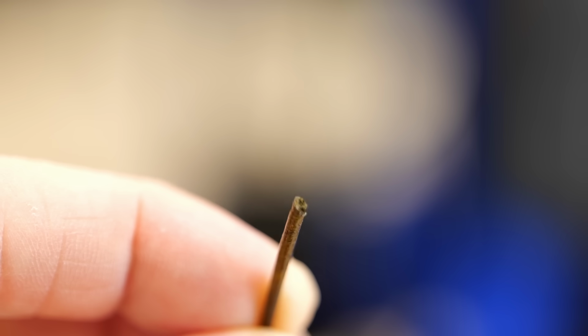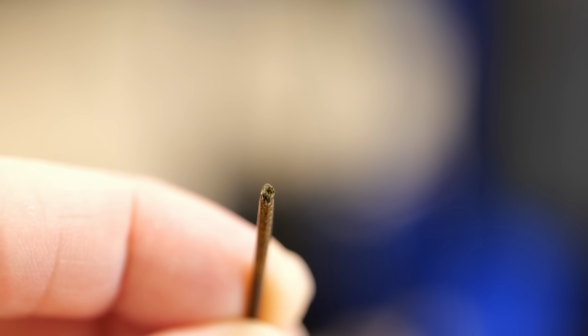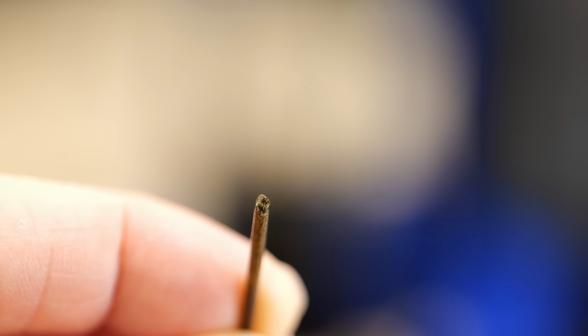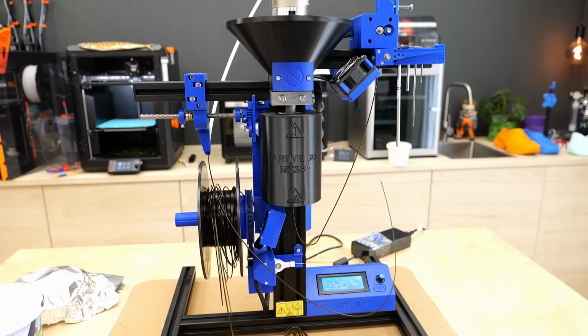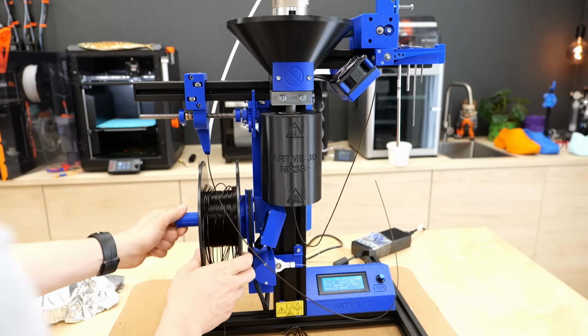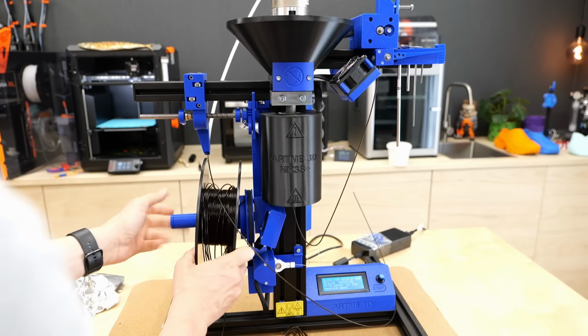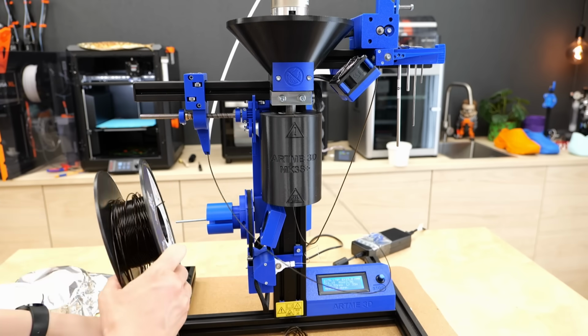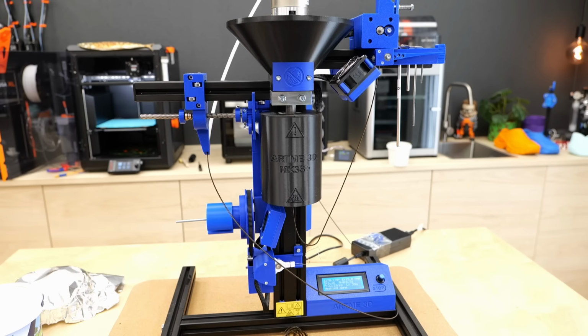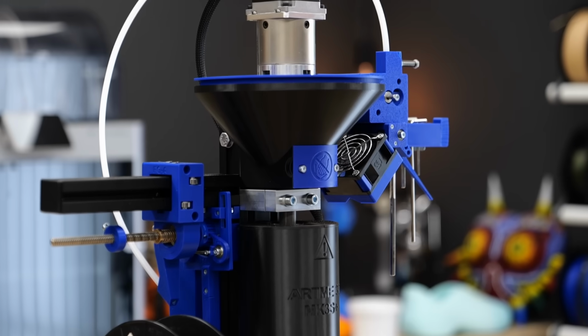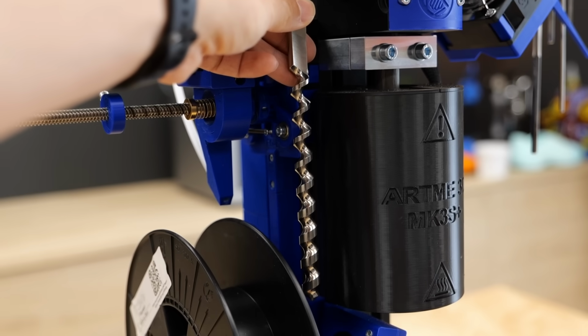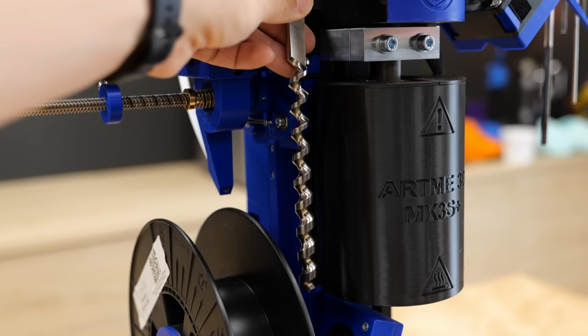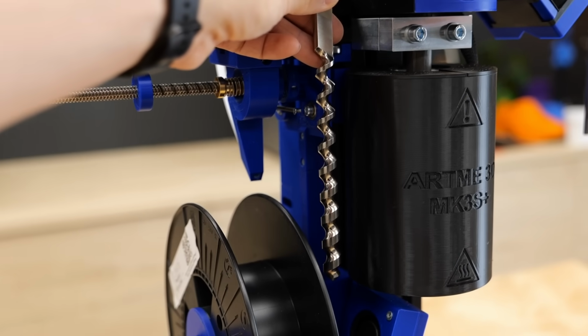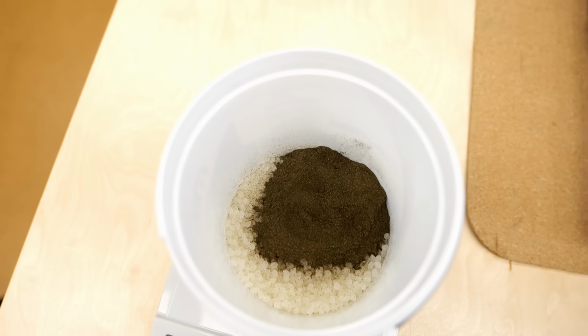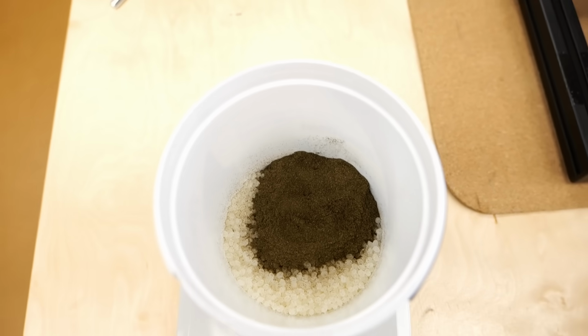Looking at the fracture surface showed that the reason again was an agglomeration of fibers that didn't properly mix within the screw extruder. So even though the filament was already of way better quality, it wasn't perfect. And just one of these agglomerates within the filament can potentially ruin a whole print, which doesn't make them acceptable. But I had one last ace up my sleeve. You see, this simple screw extruder isn't properly able to mix our fiber filler with the molten plastic. So we need to make sure that everything is already properly mixed before it goes into the extruder.